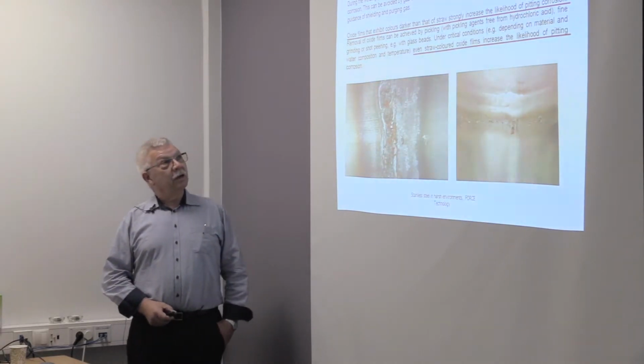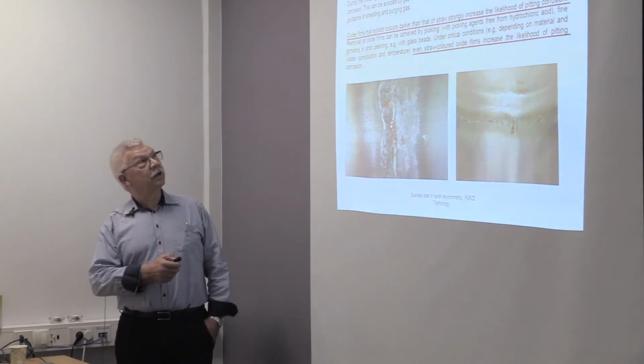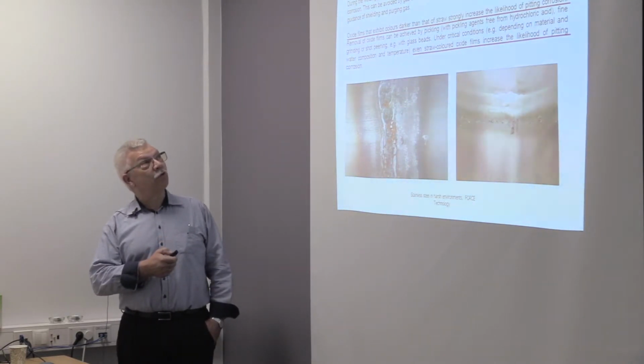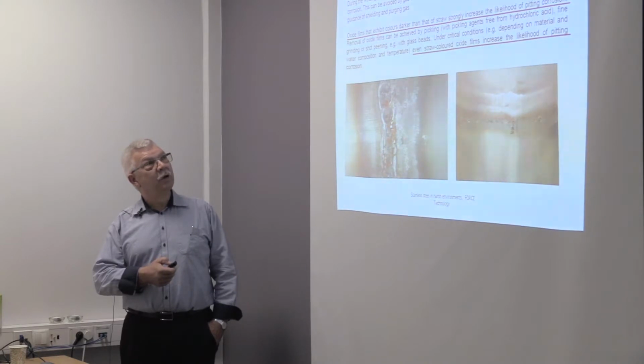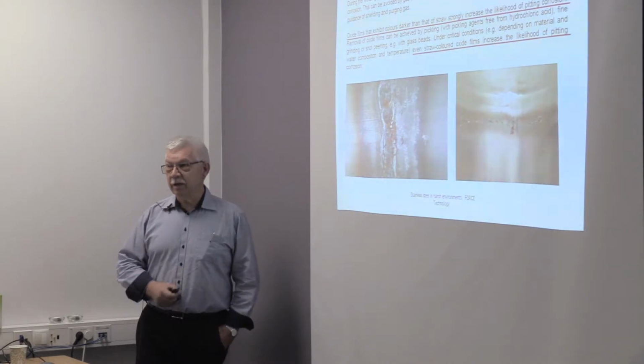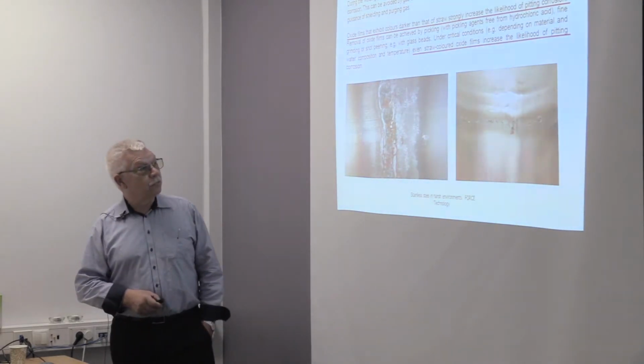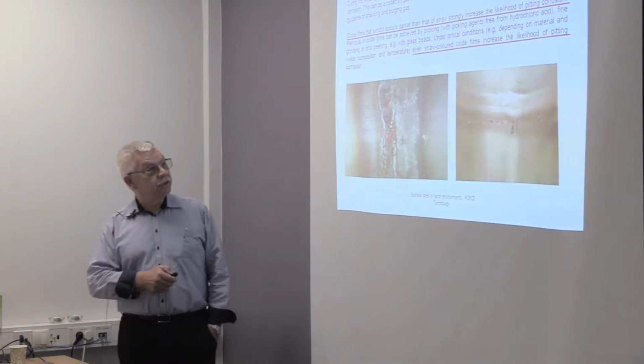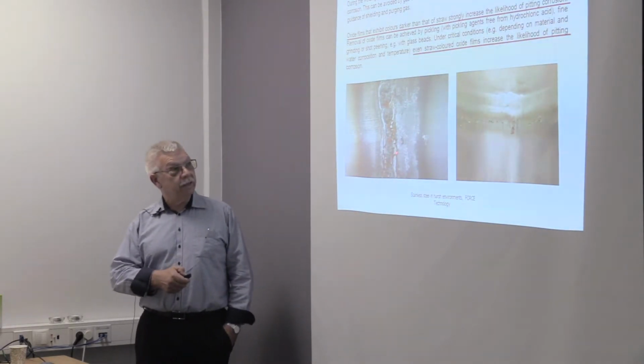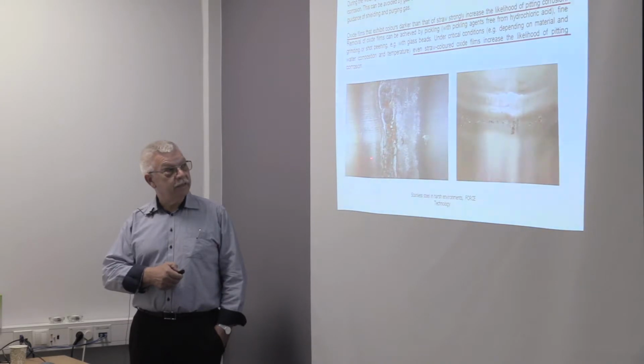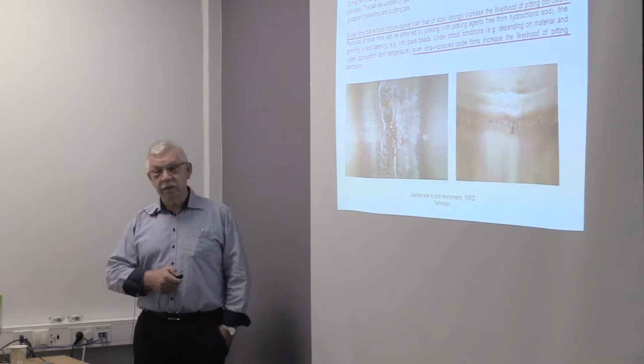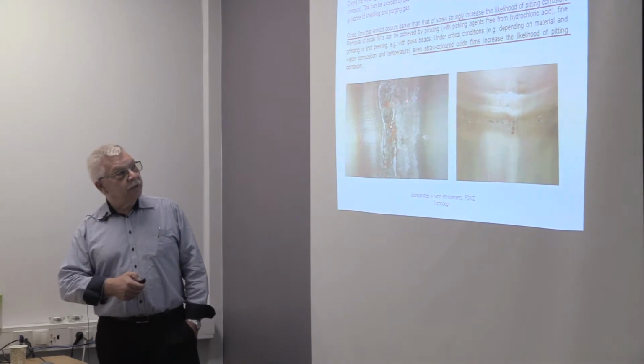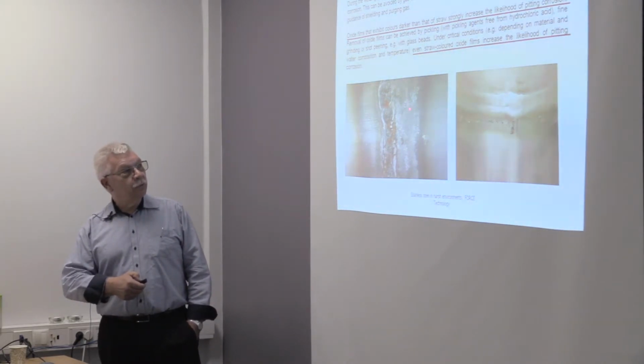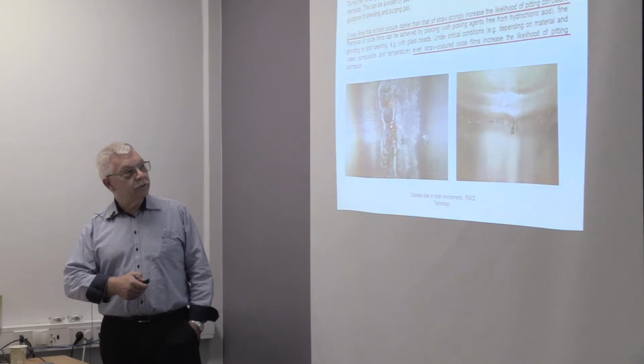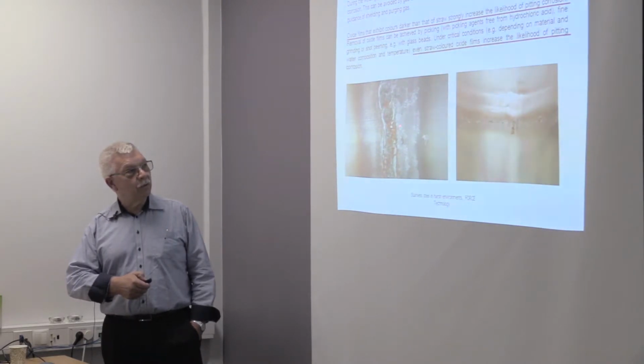About the oxidation, this standard, EN 12502, says that oxide films and scales can be formed and highly increase the likelihood of pitting. You could say that this is a weld in a stainless steel without any protection at all, full oxidation of the weld metal and of the heated surfaces, the heat affected zones on the side. And maybe you can't see it, but there are a number of pits and a few leaks in this area. I think this one is a pitting which is going all through the material.